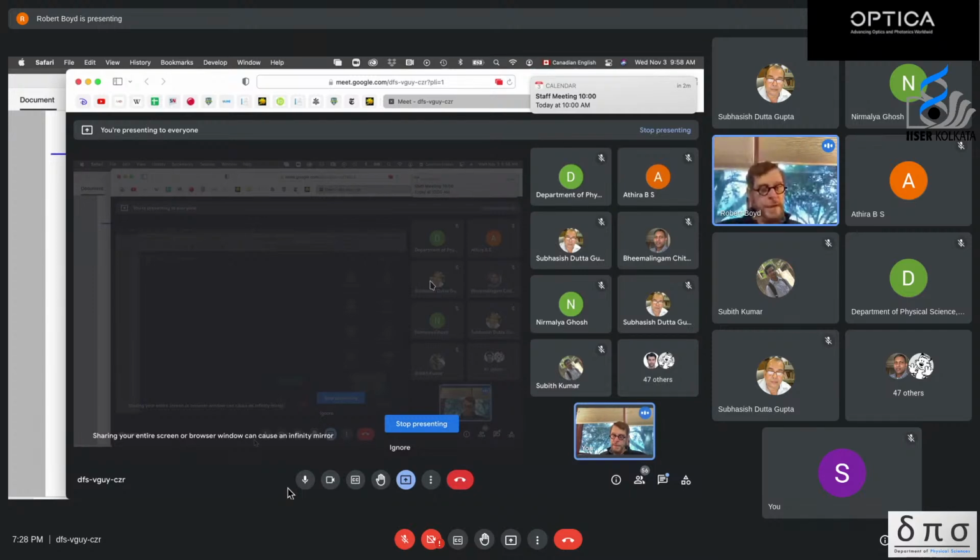So in concept, the imaginary part of epsilon can be very, very small, even in the epsilon near zero region. Second comment is that even though indium tin oxide is incredibly absorbing, the nonlinearity is so large that you only need to pass through maybe 100 nanometers of indium tin oxide to get a very large response.